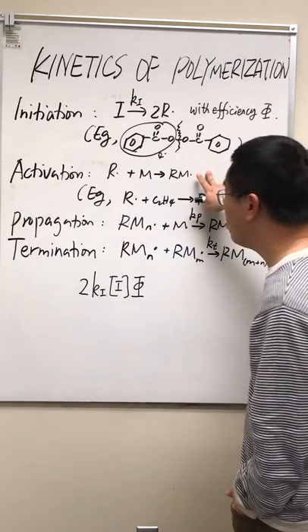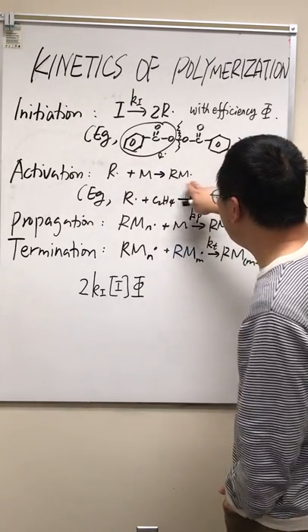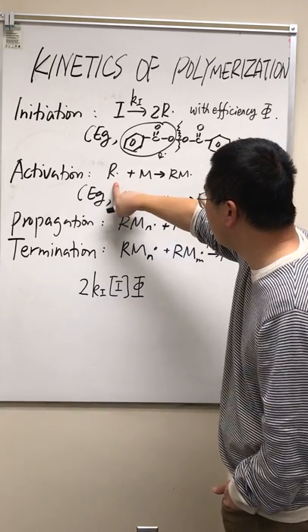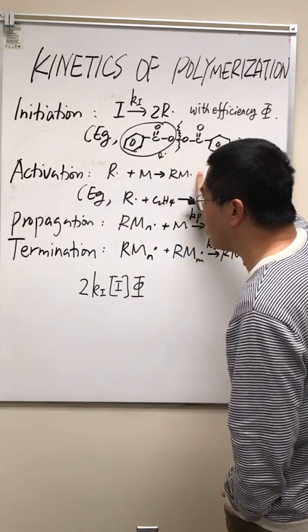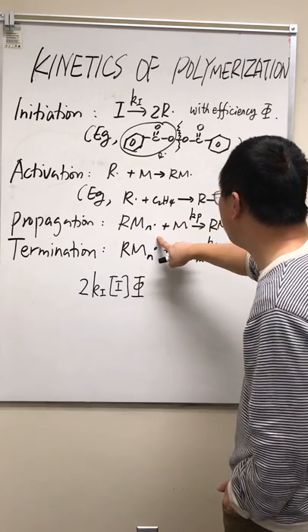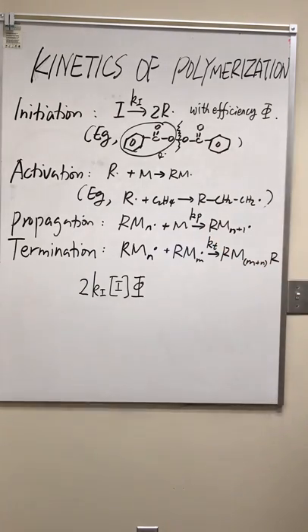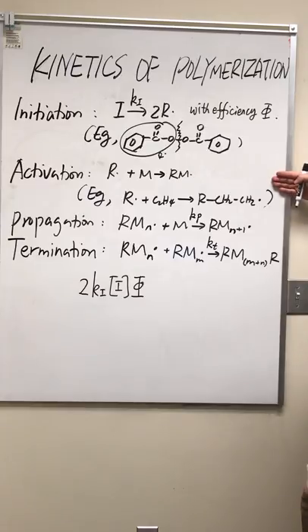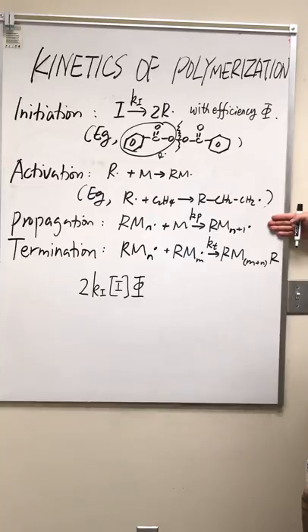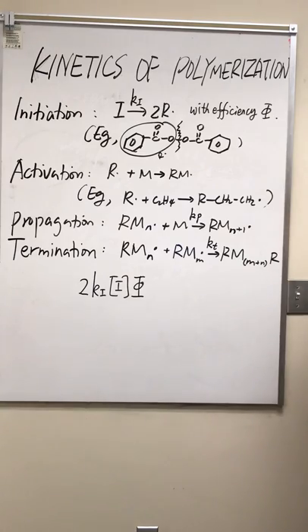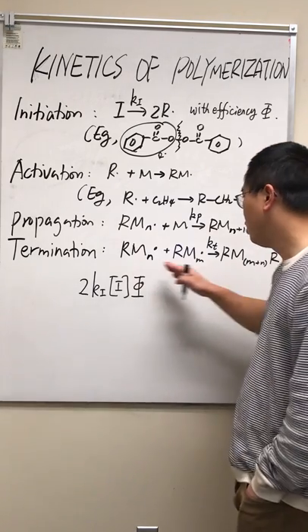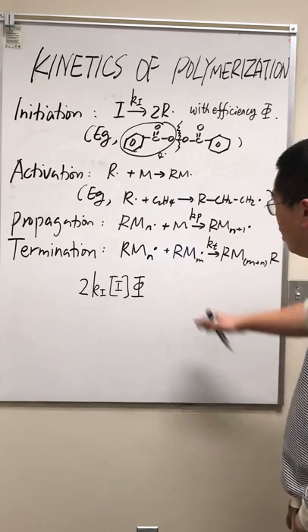Also, not all radicals can activate a monomer — some are annihilated before they can, so the efficiency φ is usually less than one. This gives us how fast radicals are produced. In the activation step and the propagation step, radicals are neither produced nor annihilated: you have one radical on the left-hand side and one radical on the right-hand side. So there is no change in radical concentration in those steps.